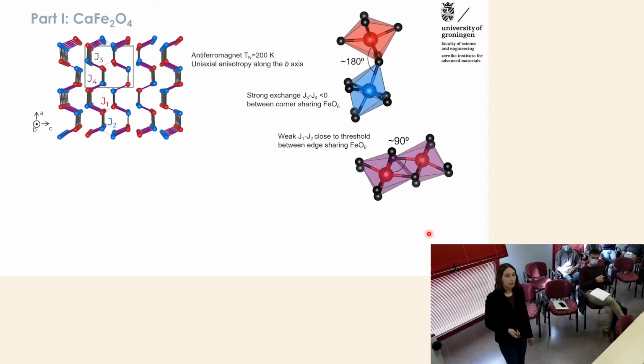So the first system I'm going to talk about today is this calcium ferrite material. It's an antiferromagnet with a Néel temperature of around 200 K. And it has uniaxial anisotropy. So all the spins here are pointing in the plane which is perpendicular to the board. There are 4 kinds of exchange interaction between the spins. And we have this J1 and J2, which are weak, and J3 and J4, which are strong. So essentially, it forms this